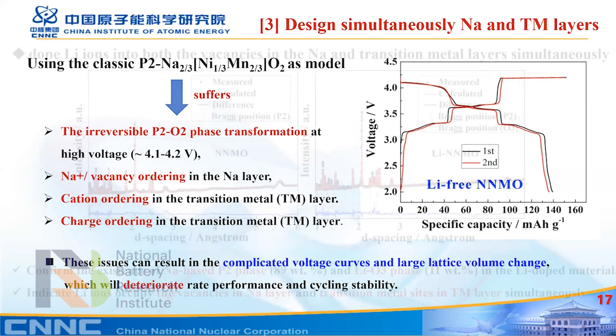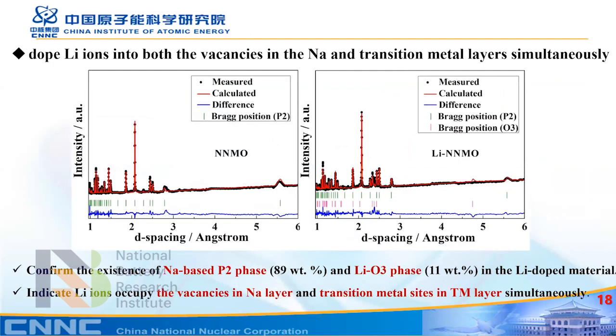Because neutron is very sensitive to the lithium element, we use HRPD, a high resolution powder diffractometer made at CIAE in China, at CARR, the China Advanced Research Reactor, to analyze the lithium location. Its resolution is very high, much better than 0.08%, the highest resolution. Also, they have 64 detectors.